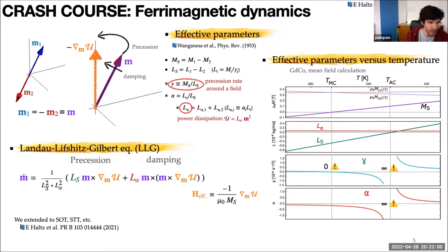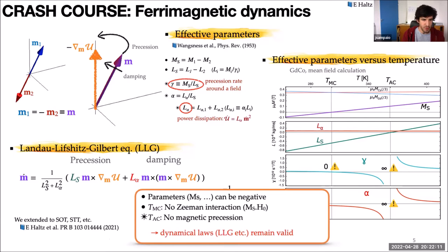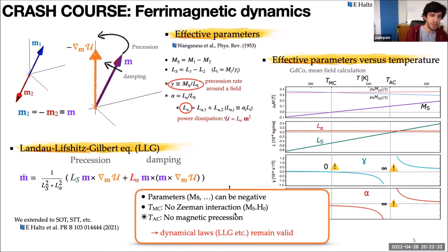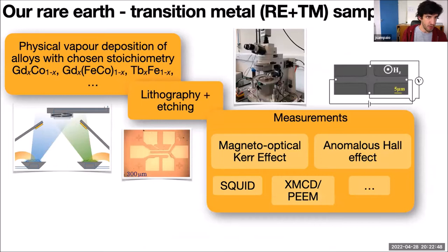What's missing is what happens when you apply current torques — this can be found in our papers. The key message from this slide is that to use ferromagnetic equations to describe a ferrimagnet, you use effective parameters. The magnetization can be negative; at Tmc there are no Zeeman interactions; at Tac there is no magnetic precession. Otherwise, the dynamical laws valid for ferromagnets remain valid for the ferrimagnet.